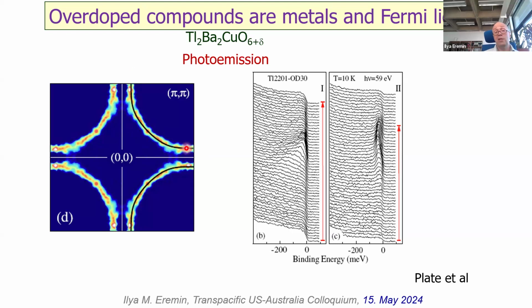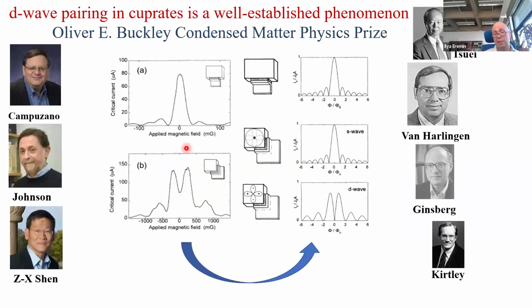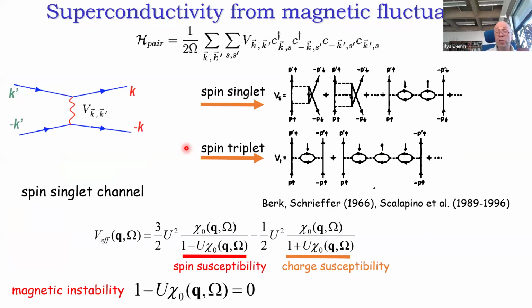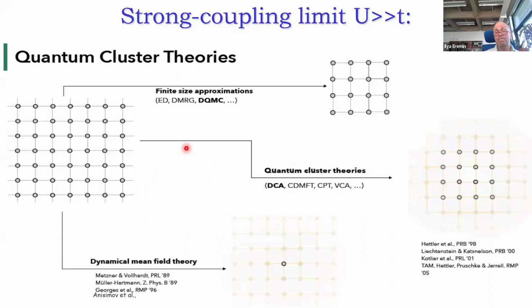Under these fields, you start to see some quantum oscillations, but the sizes of the Fermi surfaces that you get from these oscillations do not make any sense if you compare them with ARPES. Therefore, it is very likely some other phase which appears once you are entering a strong magnetic field. But what is this phase? People still don't fully understand, because it cannot be just a folding, it cannot be just a simple charge or spin density wave phase, because the size of the pocket is far too small.